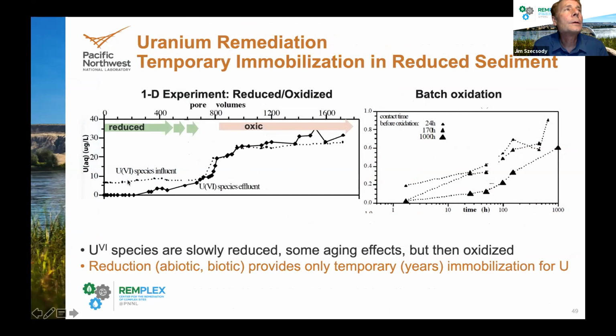And so initially, the effluent uranium concentration is removed, and then as the system becomes oxic, it's no longer removed, and uranium comes out in the system. So that's what I mean by the uranium reduction will keep uranium immobilized only for a certain amount of time, and once the system is oxidized, it'll come back out into solution.